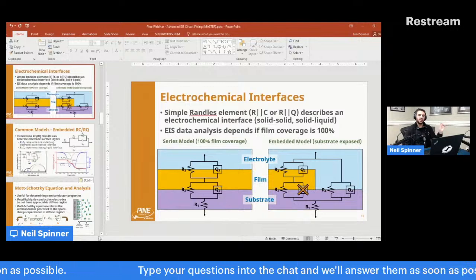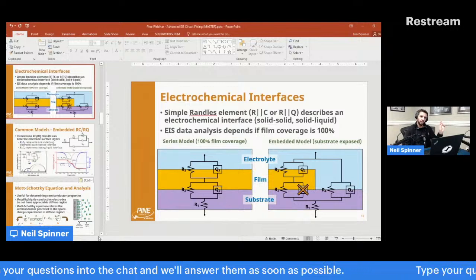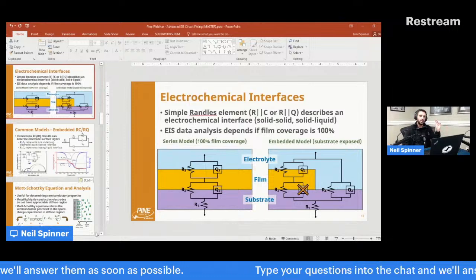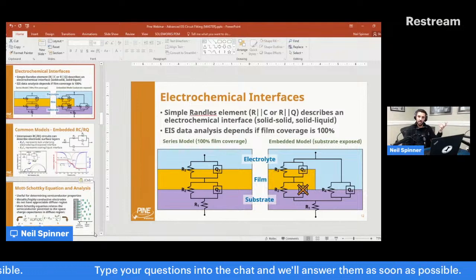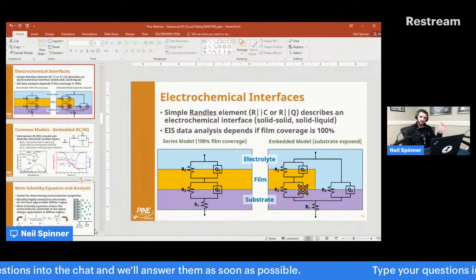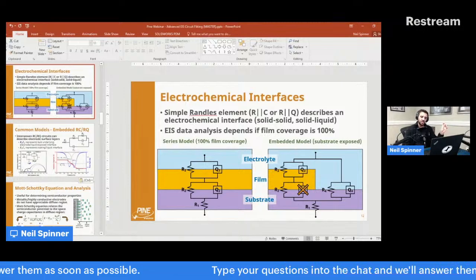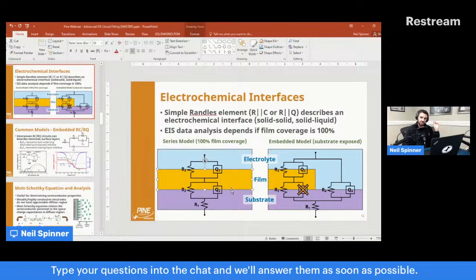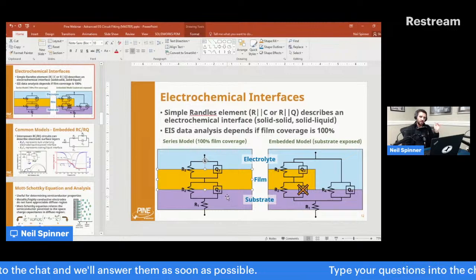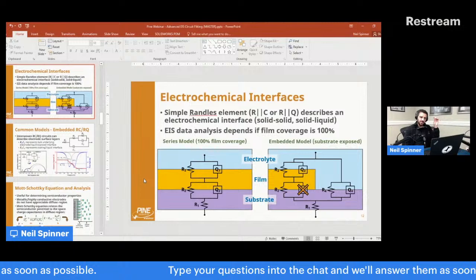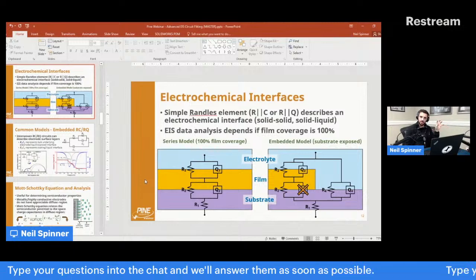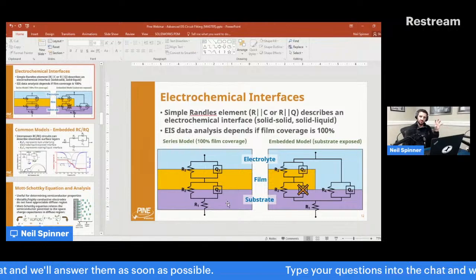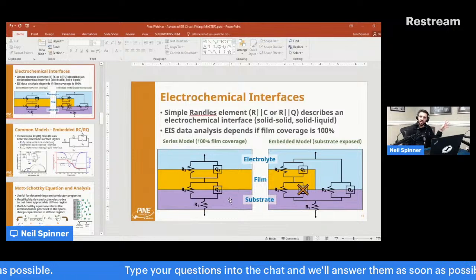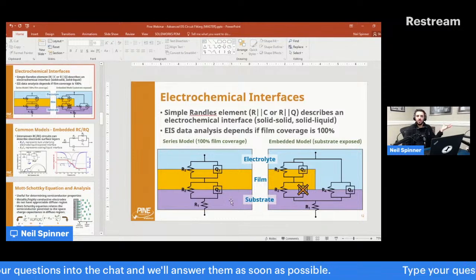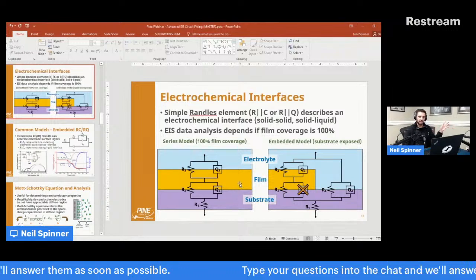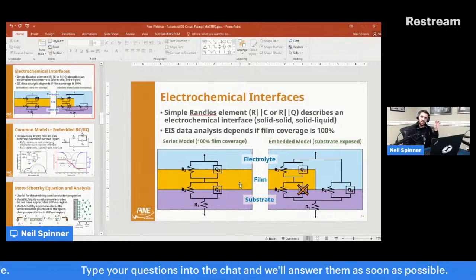Now, oftentimes you can differentiate this if you have a system where, for example, as you change the potential and change some other conditions electrochemically, the first time constant or semicircle does not change. That is probably an indication that it's this one, the substrate and the film being the first one. Because if you change the potential, I would expect everything to change except things that are physically fixed, which is the substrate and the film. If I have a substrate and film that's really tight, with no porosity or anything, and I change the potential, in theory you could have some effect there if you overly oxidize or reduce your film or polymer. But for the most part, that's physical.